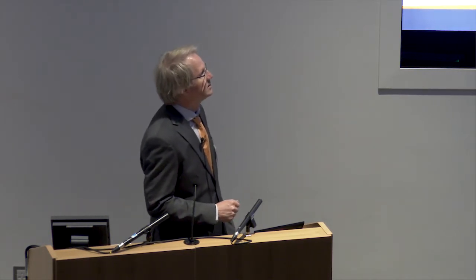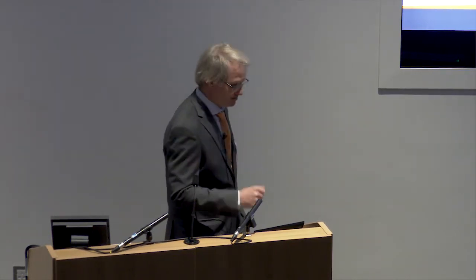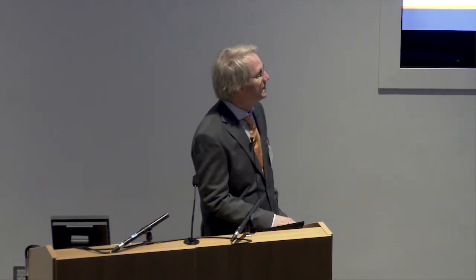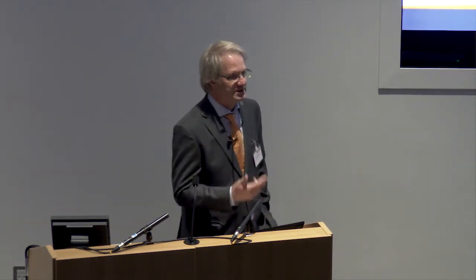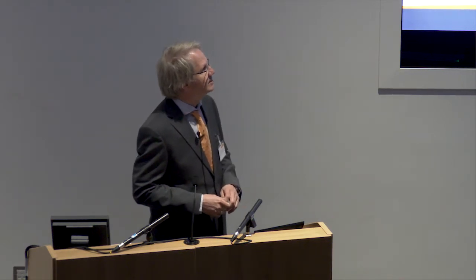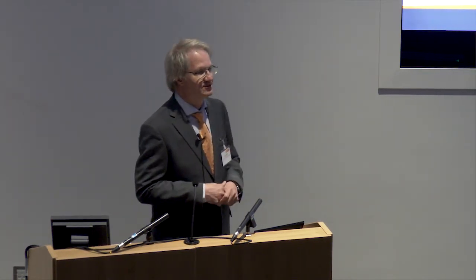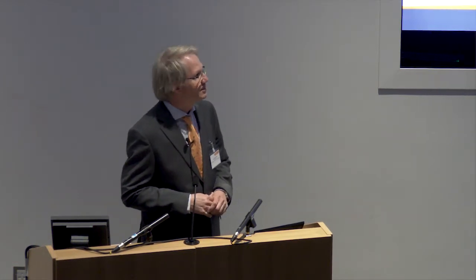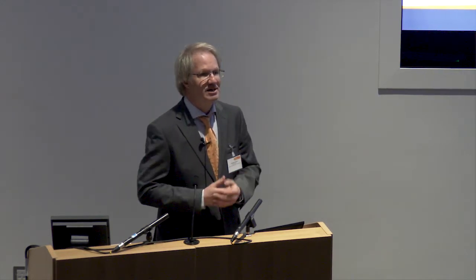Let's start with the end. You can see on the display over there that the process is running. ILT has developed a two-step process. In the first step, the overall roughness is reduced with a 400 watt laser with a relatively big laser point. And to improve the glossiness of the part, they add another process which uses only a small laser, only 250 micron diameter with 60 watts, to get the element more shiny.